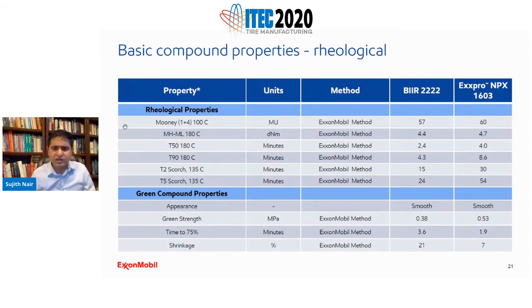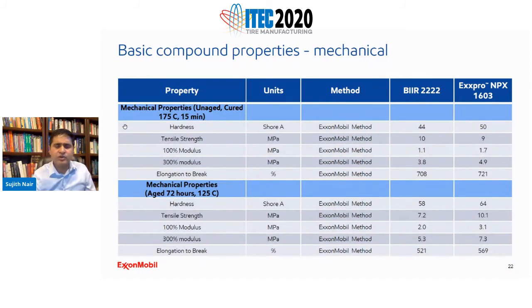If you look at the green compound properties, obviously Exxpro has a much higher green strength than that of bromobutyl. The shrinkage is much lower. If you look at the mechanical properties, most of them are almost the same. Basically, hardness is slightly higher. The tensile strength is almost the same. The elongation to break is also similar.